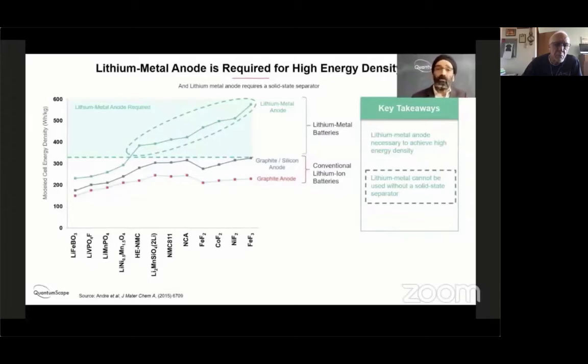People have known this in the industry, obviously, for 45 plus years, since the mid 70s. But people have also known that lithium metal is not stable with conventional liquid electrolytes. There's the dual problems of impedance growth from side reactions between lithium and the liquid. And there's the fundamental issue of dendrite growth and formation. Dendrites, as I'll talk more about later, are needle-like crystals of metallic lithium that can penetrate through the separator, keeping the anode and cathode apart, thereby short-circuiting the cell and causing a fire.